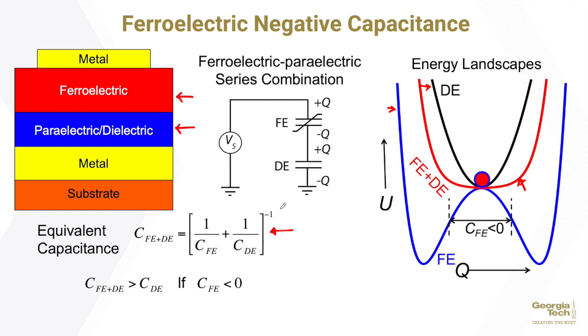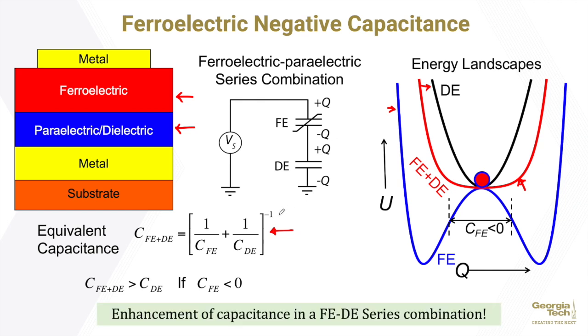On the other hand, if we take a negative 2 picofarad capacitor and one which is 1 picofarad, and put them in series, then the total capacitance will be 2 picofarads, which is larger than the positive capacitor, which is 1 picofarad. Essentially, if we have a ferroelectric stabilized in a negative capacitance state in a heterostructure with a paraelectric dielectric material, there will be an enhancement of capacitance.